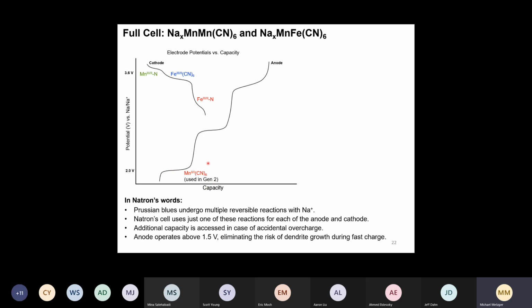And we just mentioned the manganese 2+, 1+, CN6 redox couple, which they use in their generation 2 cell. And then you see it's a nice cell which has the anode operating at around 2 volts versus sodium, the cathode operating around 3.6 volts or so versus sodium. So it's a 1.6 volt cell, and it gives you about 70 milliamp hours per gram of capacity. In comparison to that, the Gen 1 cell used the manganese 2+, 3+ redox couple, which is at a fairly higher voltage, maybe around 2.6 or so. So it only gives you 1 volt cell voltage.